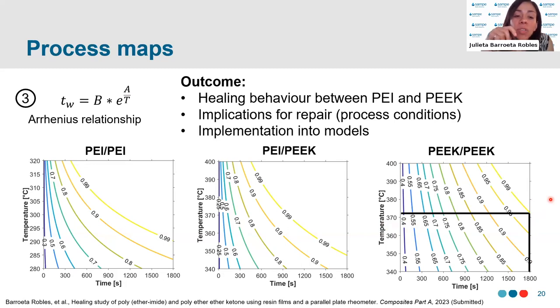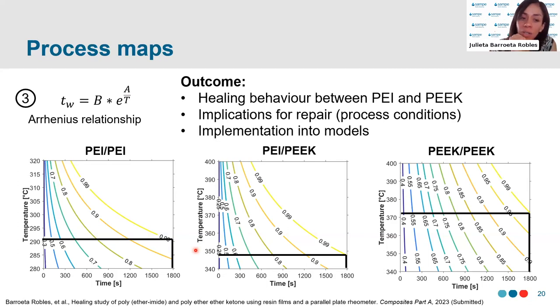So what happens then if we use PEI as an intermediate layer on PEEK? If this layer is not co-consolidated and we keep it at 30 minutes, we would need a temperature just below 350. But then what happens if we co-consolidate this layer at the processing temperature of PEEK? That way we're going to have at the interface only the PEI being joined at a lower temperature, then we can use the first process map. So that means that we would need a temperature of just above 290 degrees Celsius to obtain a degree of healing of one. Now just note that the scale of the first process map is different, just so you can see the process maps with more clarity.